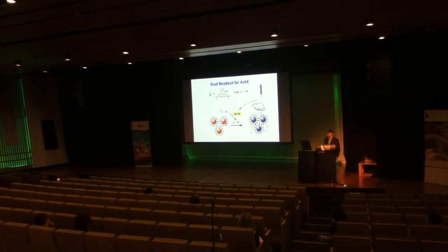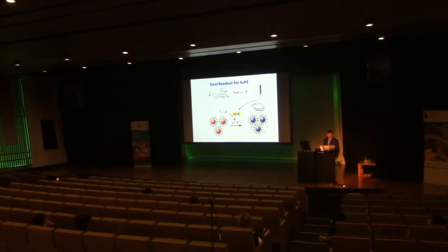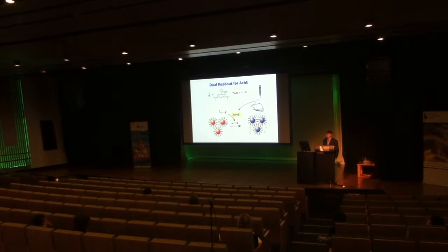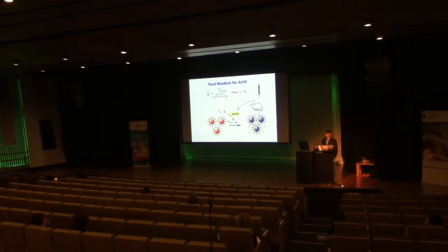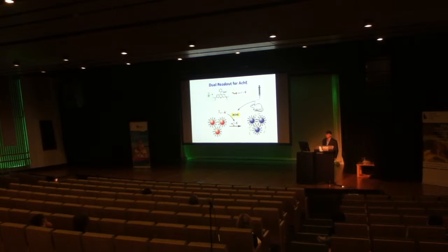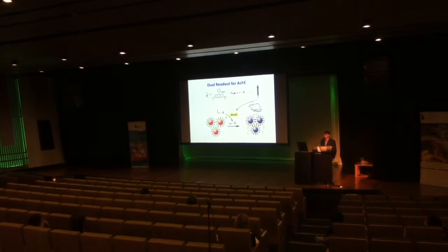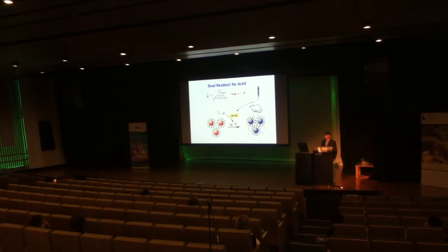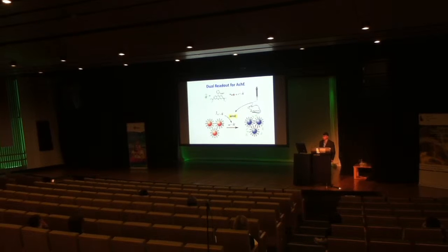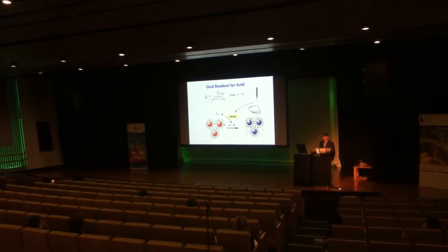But if we have ligands like this in the solution, what happens is that the thiol would bind to the surface of gold more strongly than the rhodamine. The rhodamine is believed to bind to the surface of gold via electrostatic or van der Waals interactions. Because the sulfur-gold bond is much stronger than that, it is believed to replace the rhodamine from the surface of the gold.